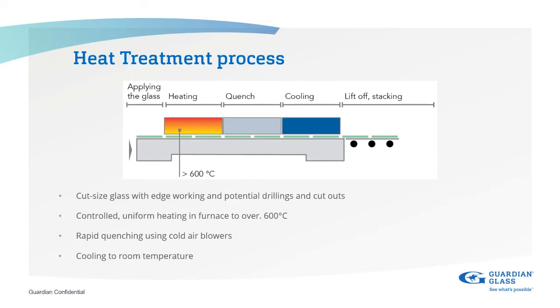This is where the glass, once it's finished the cut size and the arris edge work, and it's been cleaned efficiently, will then be loaded into the onload and then into the furnace. For 6mm, the heating time is approximately 240 seconds, plus or minus 5 seconds.